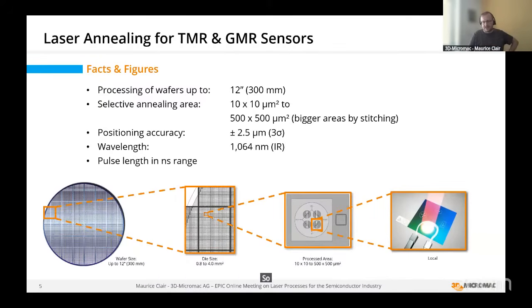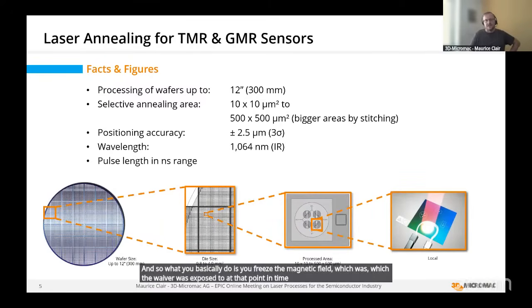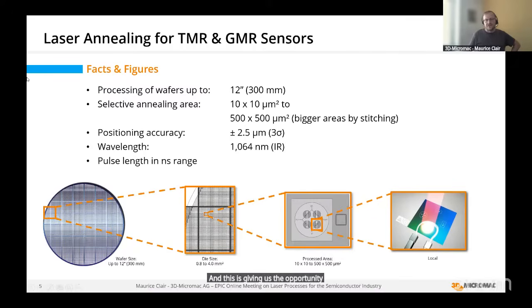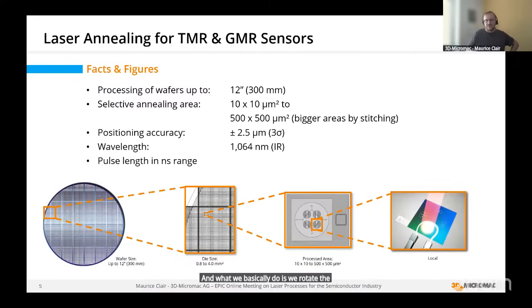So what you do is basically you freeze the magnetic field which the wafer was exposed to at that point in time. And this is giving us the opportunity, now it's depicted in the bottom. If you look at the die, on this die, you have this Wheatstone bridge, and in this Wheatstone bridge, you need either 2 or 4 different directions of your magnetic field. We can do up to 32 in the end, but most of these designs use a Wheatstone bridge with 2 or 4 orientations. And what we basically do is we rotate the magnetic field and we process the wafer multiple times.